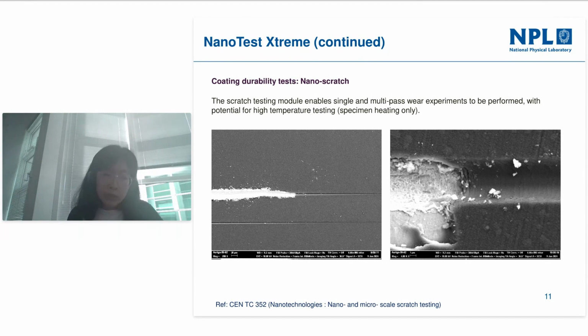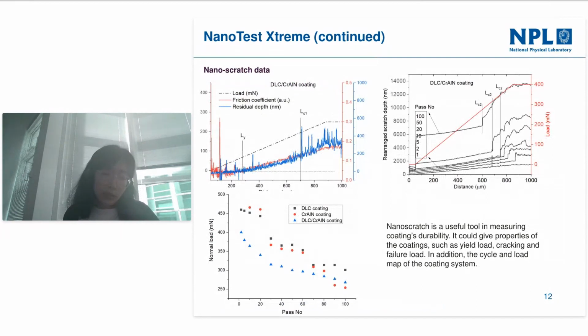There are more details about the nano and micro scratch test in the CEN standard, which was developed recently, led by my colleague Yan Piao, with Mark J leading the standard development. And in addition to the images observed after the test, the record of the scratch path, topography, and the friction force gives a matrix of parameters to characterize the coating wear resistance.